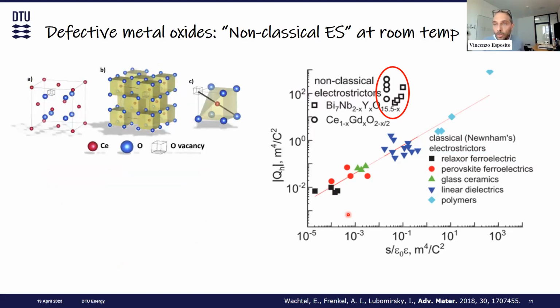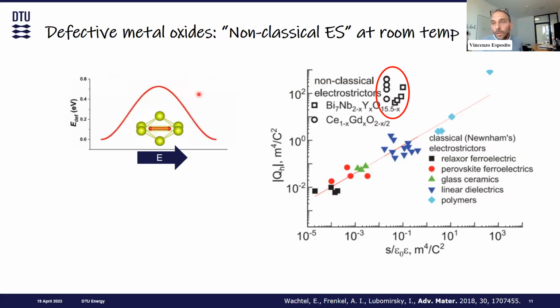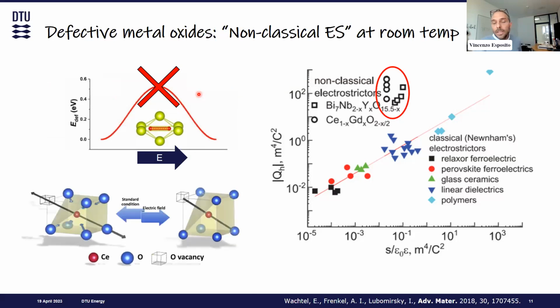But let's try to recap what is happening, for example, for cerium oxide, which is already in this plot. We have a fluorite structure with the oxygen vacancy. So our crystal is not perfect. It is missing an important component. And if we have a strong electric field at high temperature, we usually move this defect. But now we cannot move it because we are at room temperature. There is not enough thermal energy to do this job. And the result is that when we apply an electric field, the material starts to strain. And the strain goes back depending on the intensity of the electric field.